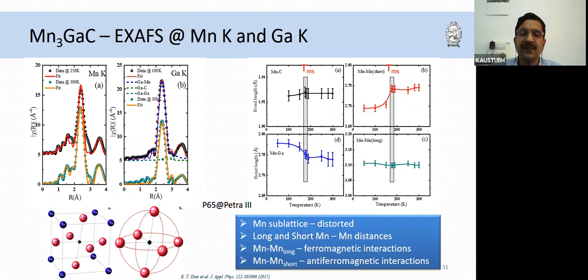So what we said was, in these antiperovskites at lower temperatures, the manganese sublattice is distorted. There are long and short manganese distances. The long manganese distance is responsible for ferromagnetic interaction. The short one is responsible for the antiferromagnetic interaction. And this collapse of manganese at the first order transition should have resulted in a symmetry change, which is then accommodated by the lattice by increasing itself and providing that much needed space for the manganese octahedra to distort.